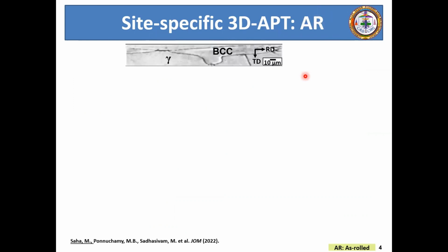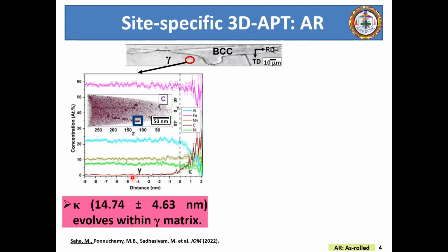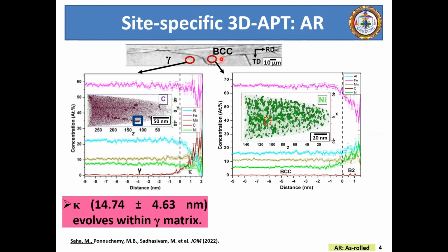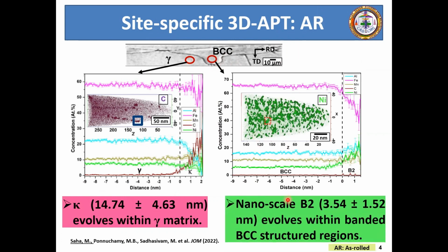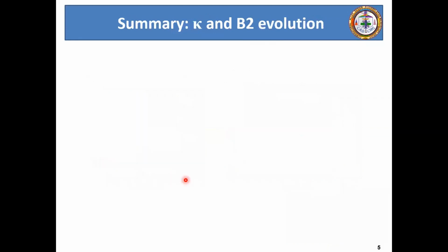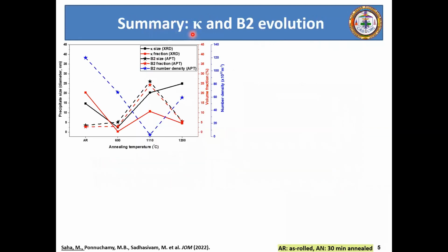And what we can clearly observe is that from within the gamma phase, we have the localization of nanoscale kappa precipitates of average size nearly around 15 nanometers evolved within the gamma matrix, whereas from within the BCC phase, we have the evolution of nanoscale B2 precipitates of average size nearly around 3.5 nanometers localized within the banded BCC structured regions. So now, having further performed this investigation in the other annealed conditions, this particular plot shows the variation in terms of the precipitate diameter, their volume fraction, and their number density as a function of the annealing temperature for the kappa and the B2 precipitates.